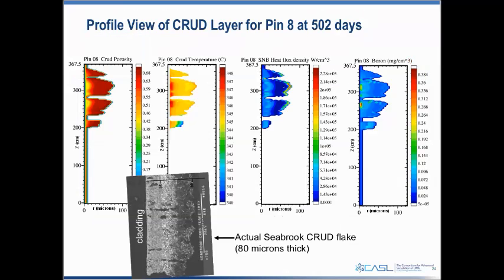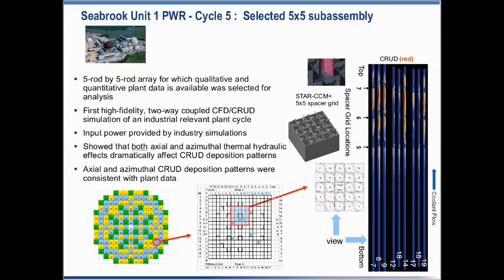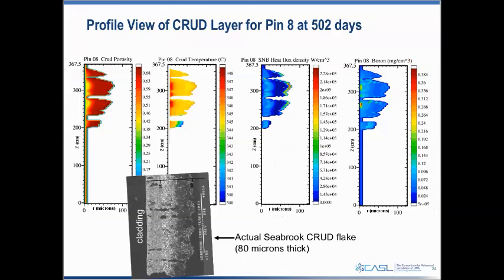This provides a profile of the crud layer on an individual fuel pin, for one of the fuel rods in that 25-rod simulation. We did have crud scrapes from Seabrook, and the actual crud thickness was approximately 80 microns thick on some of the thickest crud we found, or a little over 3 mils.